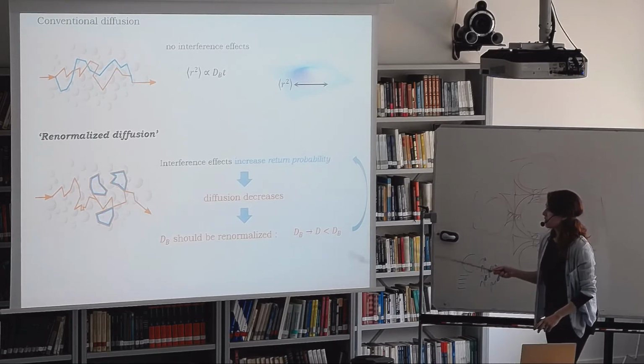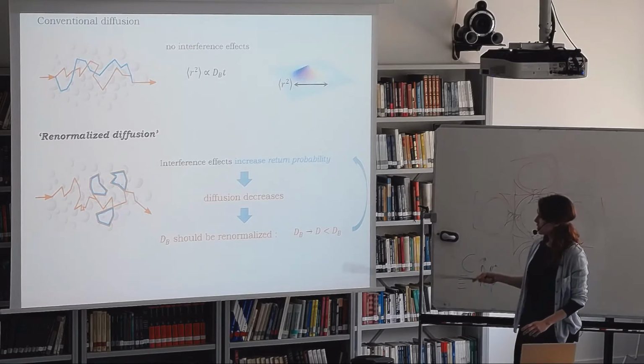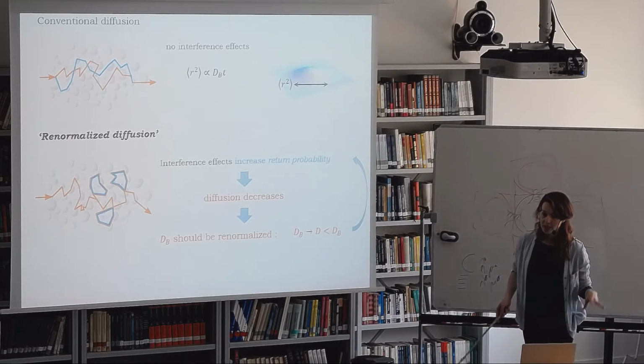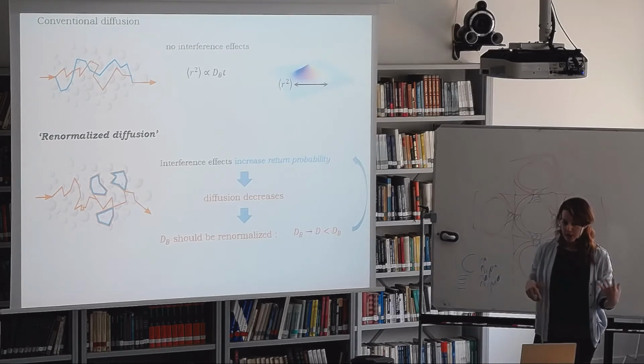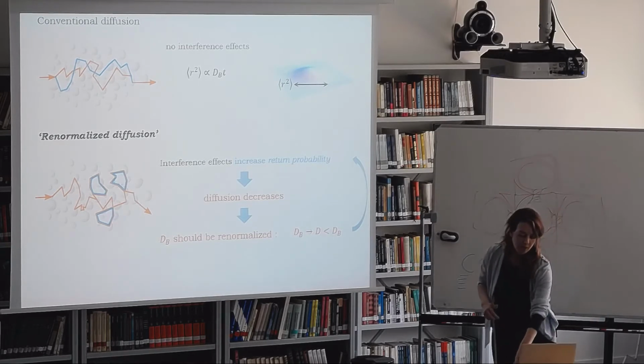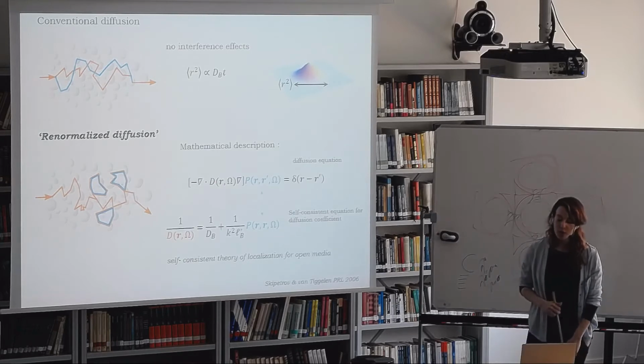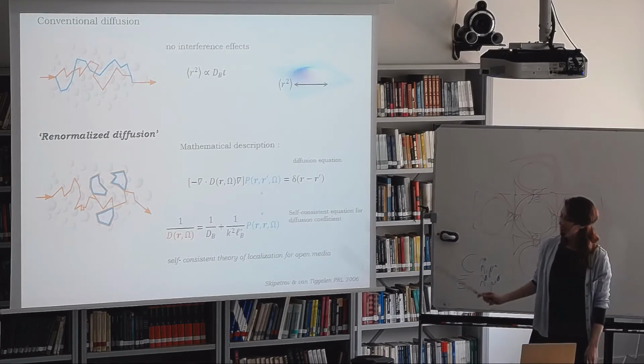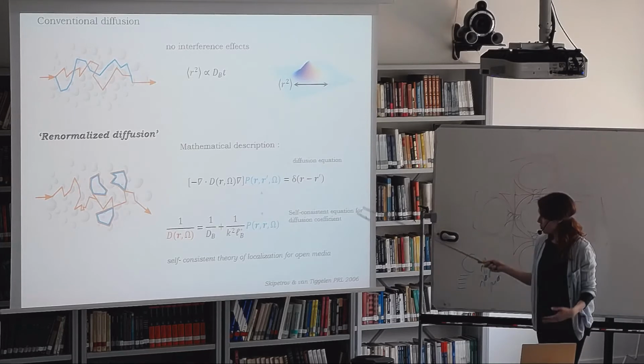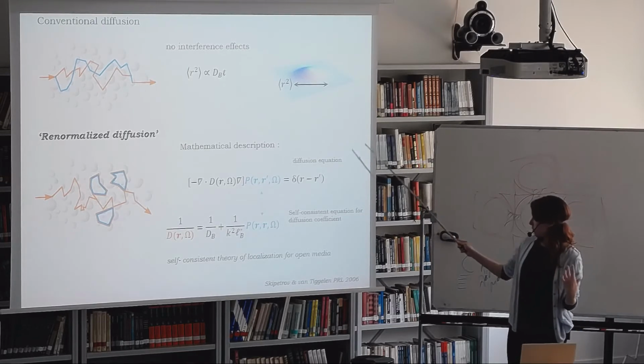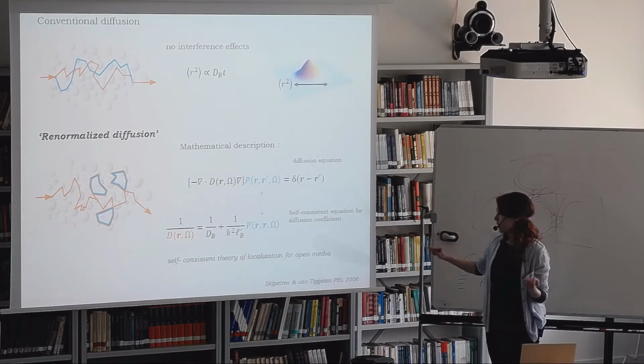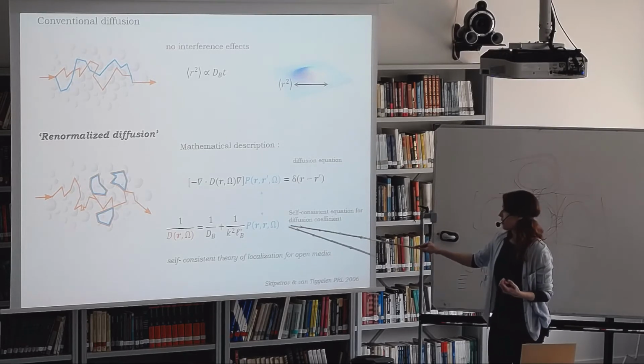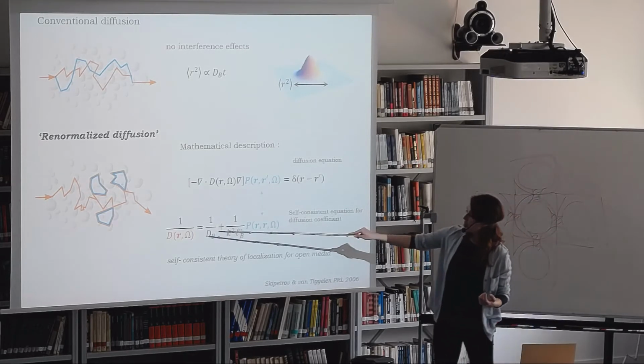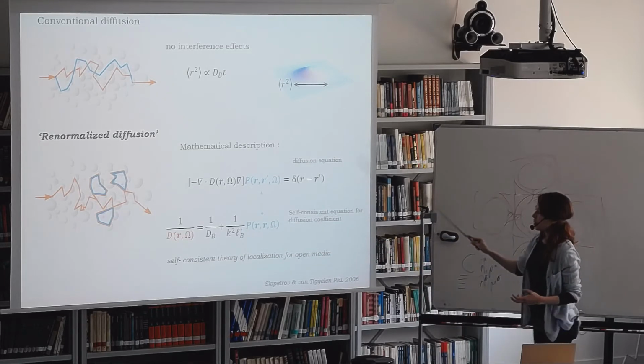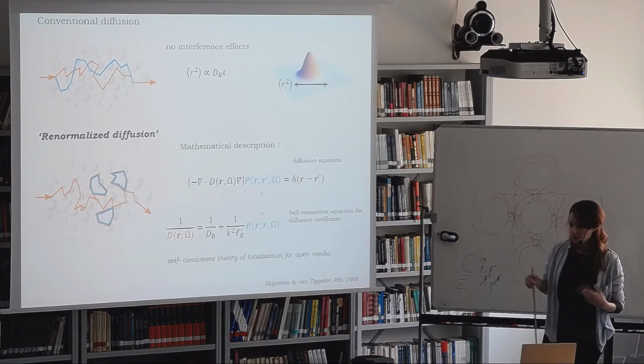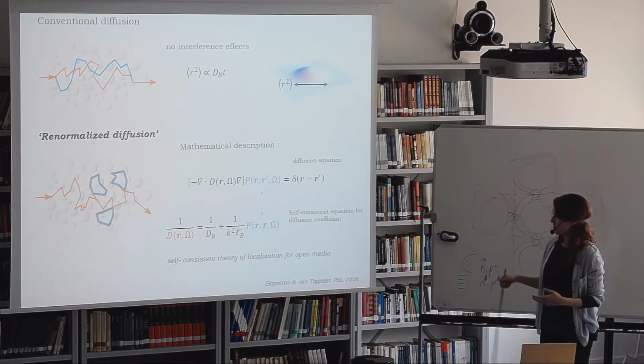And so you have this process which is actually successively happening. The longer you spend inside the sample, the more the diffusion is renormalized and it gets smaller and smaller. If we want, we can describe this mathematically using a diffusion equation to which the solution is a return probability. And then we can also have another equation which links an increase in return probability to a decrease in the diffusion coefficient. And then one solves these two equations self-consistently to find the diffusion coefficient as a function of time.